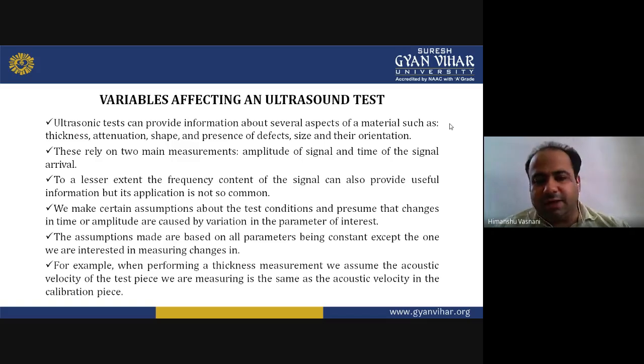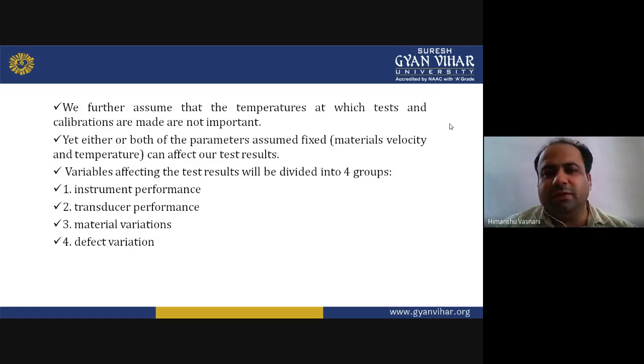For example, when we perform a thickness measurement, we assume that the acoustic velocity of the test piece we are measuring is the same as the acoustic velocity in the calibration. We assume these test conditions and then go for the test. There is also temperature. We also assume that the temperature at which the test and calibrations are made is not important. Yet either or both of the parameters are assumed fixed. Material velocity and temperature can affect our test results. So the variables affecting the test results will be divided into four groups.